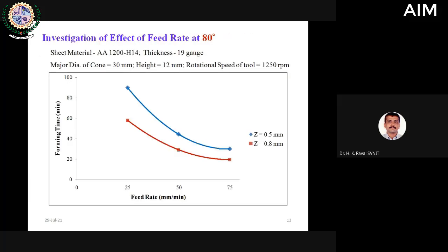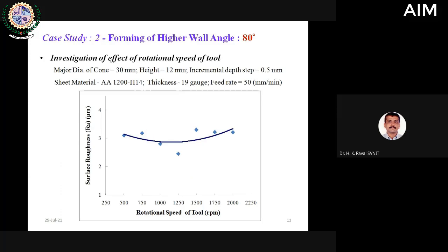Then we tried with a higher angle also, that is 80 degrees, and at 80 degrees we get an almost similar trend: around 1250 rotations RPM, the surface roughness is minimum, so the surface finish is best. So there is one decision parameter: for the detailed study, one can use an RPM in the range of 1000 to 1500, maybe close to 1250. That gives a good surface finish.